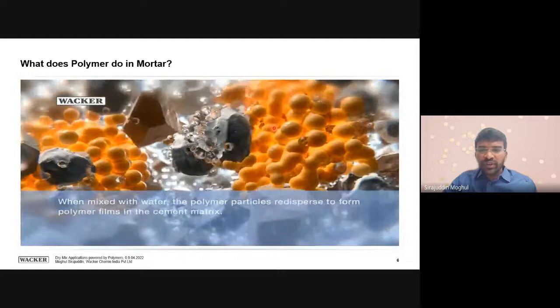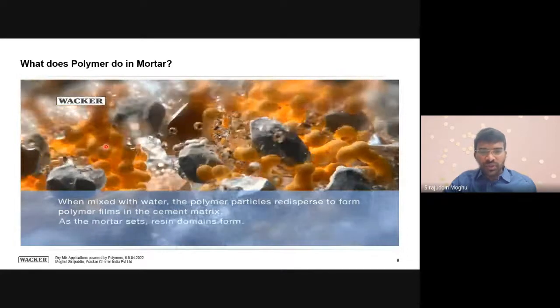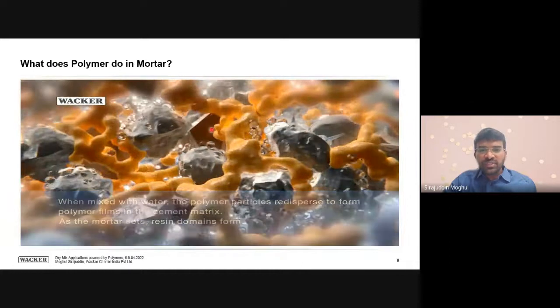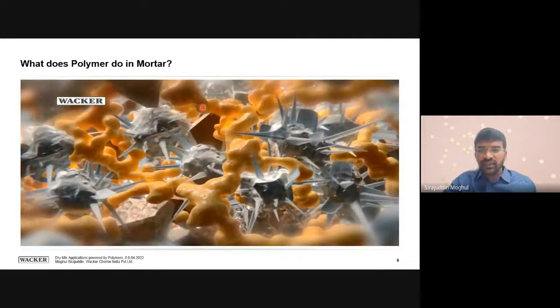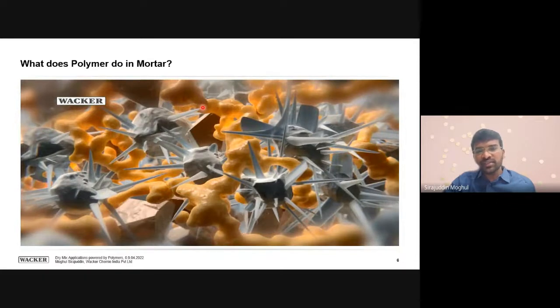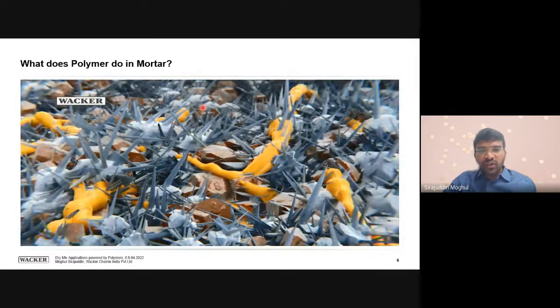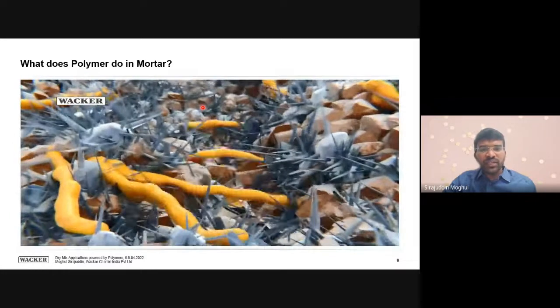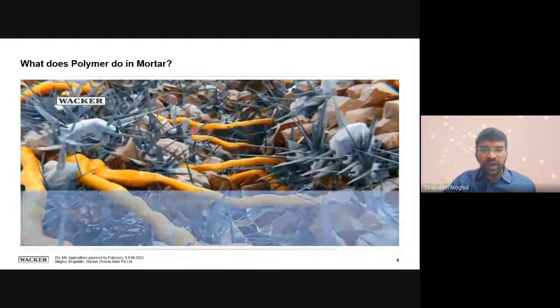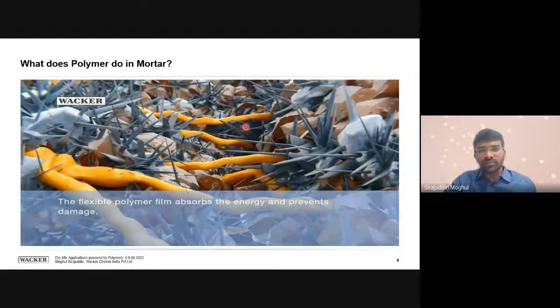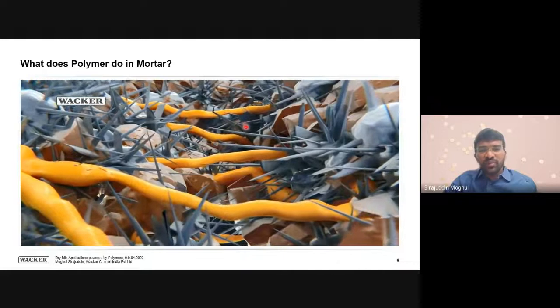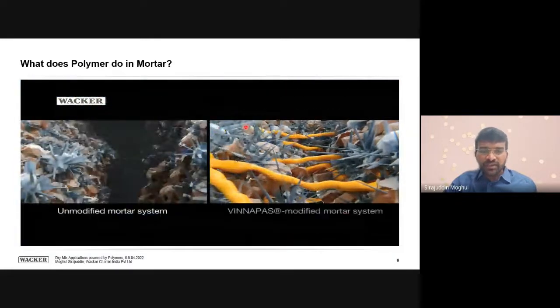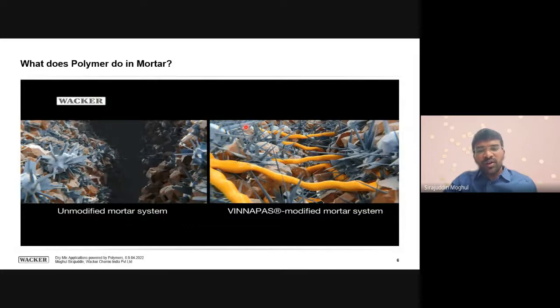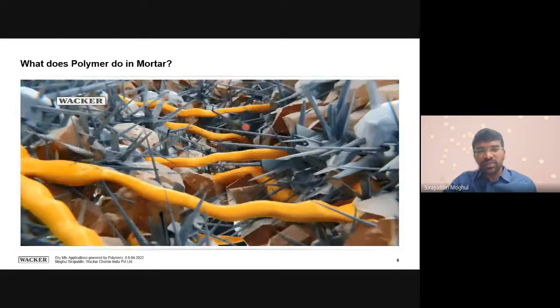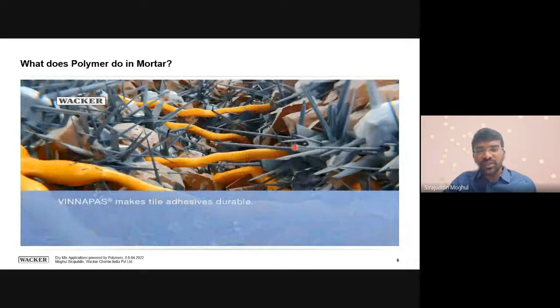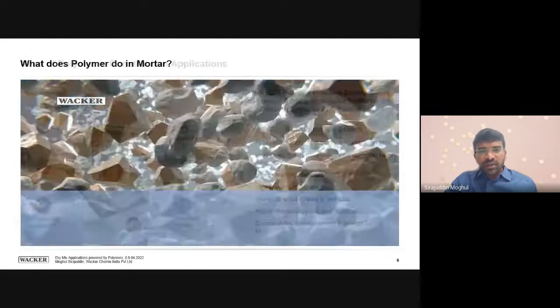When it comes into contact with water, it gets dissolved in the matrix, and it forms a mesh-like or net-like matrix inside the mortar, and it undergoes the reaction. Now, when this mortar comes in contact with any stresses, it binds it and keeps it intact. So that is how polymer modified mortar is advantageous, and that is why we need to use polymer in the cement matrix, like why we need to use a polymer in cement mortars or cement based applications.